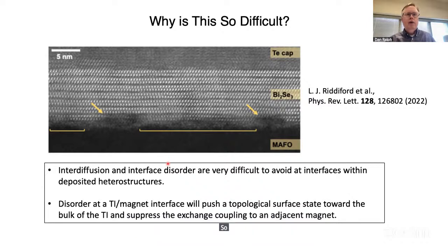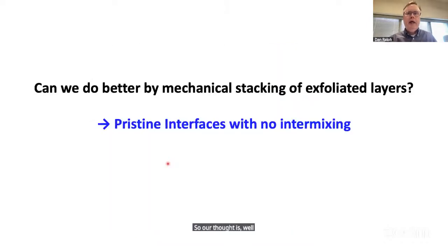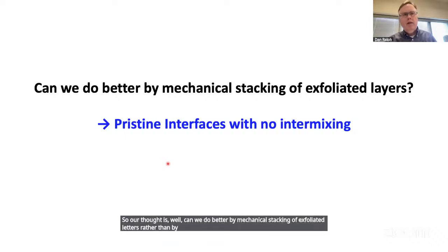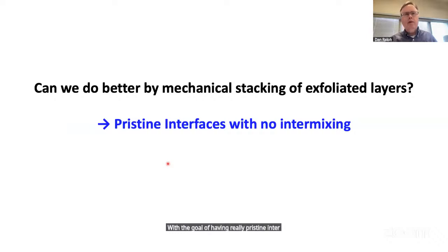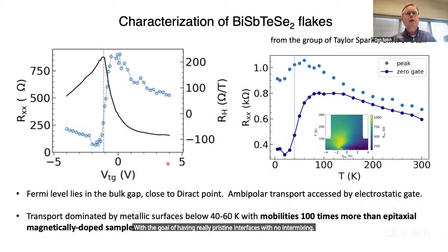So our thought is, well, can we do better by mechanical stacking of exfoliated layers rather than by using MBE kinds of materials, with the goal of having really pristine interfaces with no intermixing? Okay, so that's what we've done. To start with, we use very high quality quaternary topological insulator materials grown by the Taylor Sparks group of the University of Utah. So bismuth, antimony, tellurium, selenium-2.